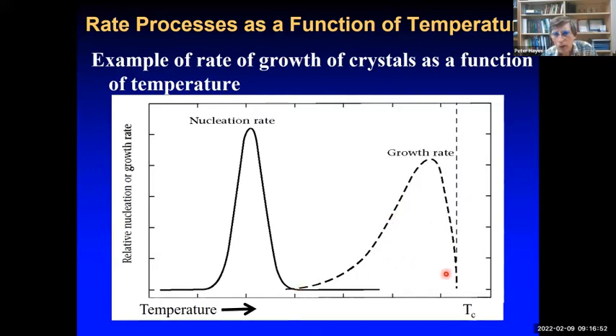So what's happening here? On this side of the line, we have high mobility, and the thermodynamic driving force for a reaction is increasing. And so the rate is increasing. When we get to this situation at lower temperatures, we find that the mobility of the species in the system is decreasing at a faster rate than the increasing driving force. And so overall, the rate will decrease.